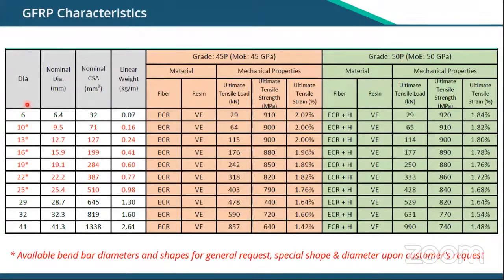As you can see in our range for permanent application, we go from diameter 6 to 41 mm. And if you have a quick look at the ultimate tensile strength, this is connected to what I mentioned earlier. The smallest diameter will have the highest strength in MPa, while the biggest one will have the lowest. So again, here two examples of two different grades, but that's typical what you would expect.